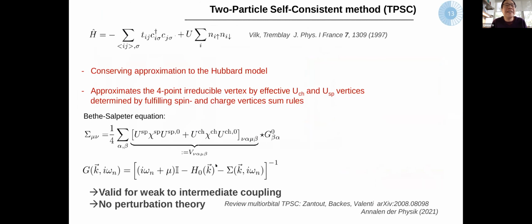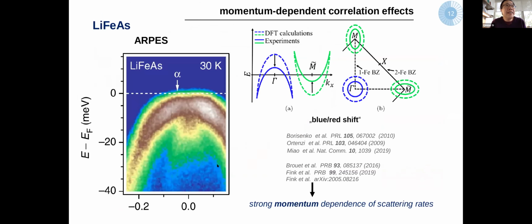Yes. So lithium-iron-arsenic. It's interesting to ask how it compares with FeTeSe, a material which is of a lot of interest for a variety of reasons. There, actually, it was shown that you have this orbital selectivity, but at the gross level, you can just raise the temperature and see that the spectral weight of some of these orbitals goes away, and the others don't. So dxy is where it goes away, and there's some temperature scale for that. And that was one of the indications where local interactions play an important role.